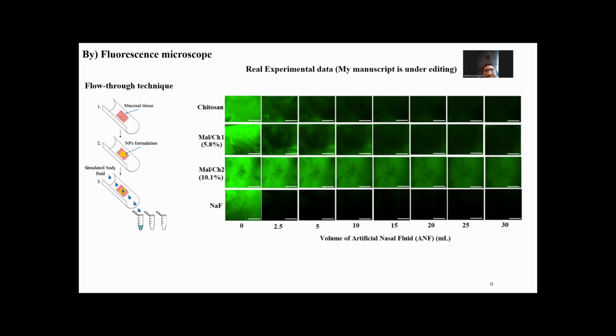I have here, for example, 4 materials. The chitosan on the top, the second one, the maleimide chitosan, with a different degree of substitution, like 5.8, another maleimide substitution, 10.1, which increases the amount of maleimide group. The last one is sodium fluorescein as a negative control. After washing with artificial nasal fluid, after 2.5 ml, the fluorescent green color of chitosan and all of them should be decreased. But the negative control is already black from 0 until 30 ml. For chitosan the fluorescence intensity is decreased, but the maleimide still has green light until the end, especially 10.1%, until the 30 ml. Next slide, please.